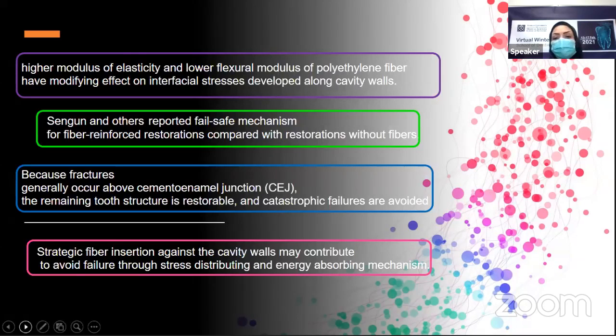Sengun and others reported a fail-safe mechanism in the wallpapering technique. It means that fracture generally occurs above the cemento-enamel junction in FRC restorations, especially in the wallpapering technique. And it shows that the remaining tooth structure is restorable and catastrophic failures are avoided. The strategic fiber insertion against the cavity wall may contribute to avoiding failure, and it does so with stress distribution and an energy-absorbing mechanism.